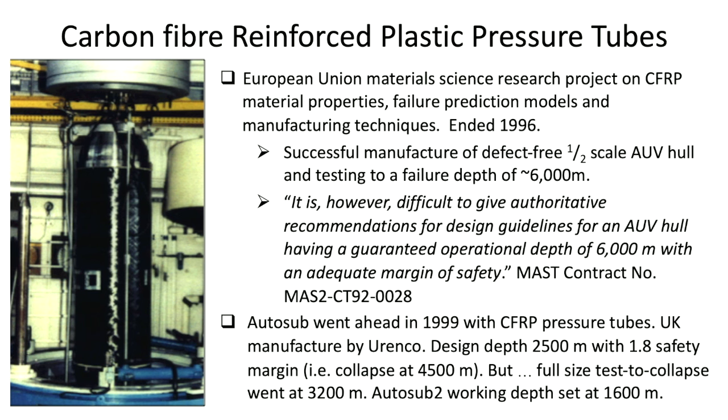The picture that's going round is from the Defence Research Agency, where they wind the cylinder, and you can see the process in this photograph, where individual fibers are wound onto a mandrel, which then forms the tube, and those fibers pass through a bath of epoxy adhesive, araldite. And those fibers pick up the adhesive, they travel onto the cylinder, and it's wound at a cross angle of 55 degrees to try and maximize that property.